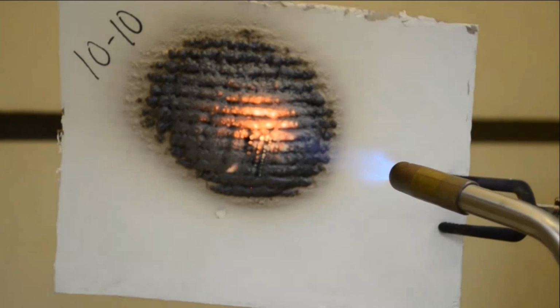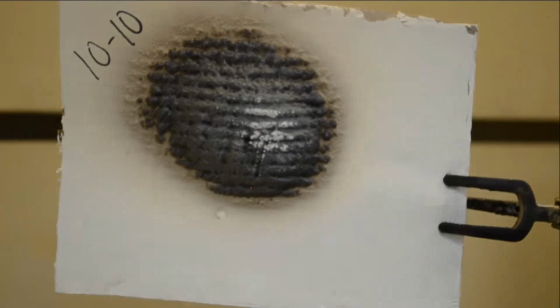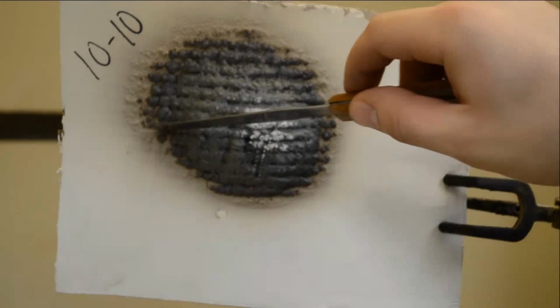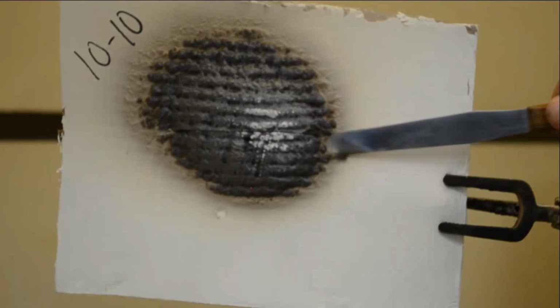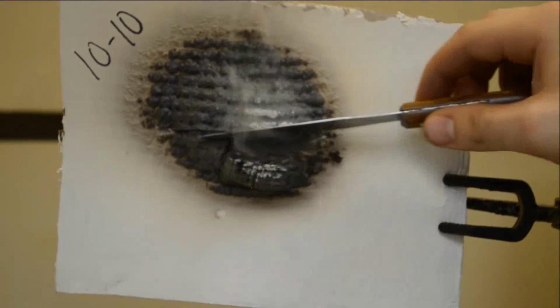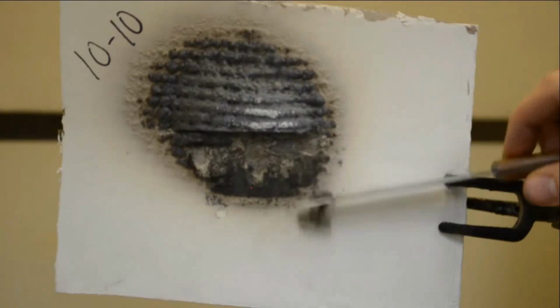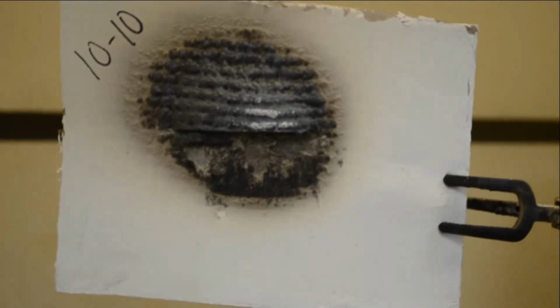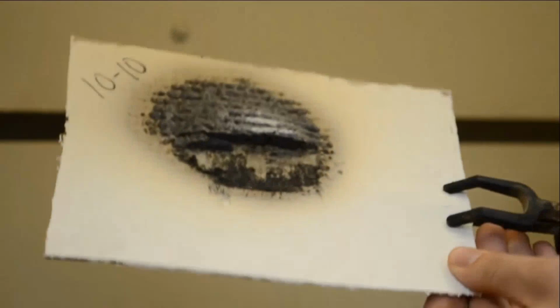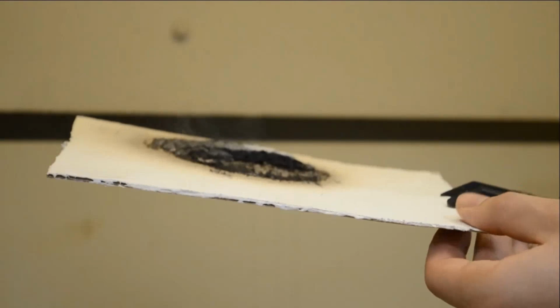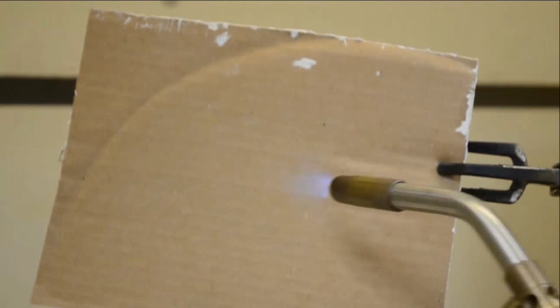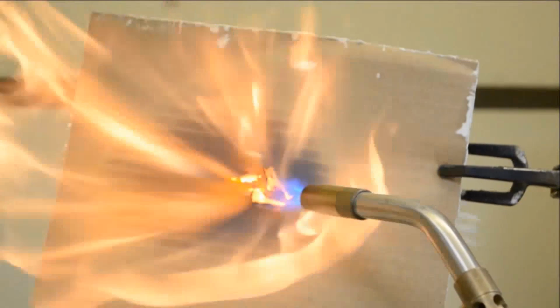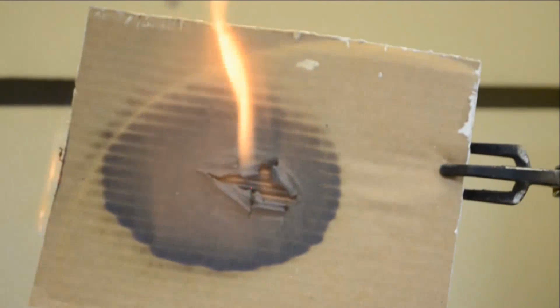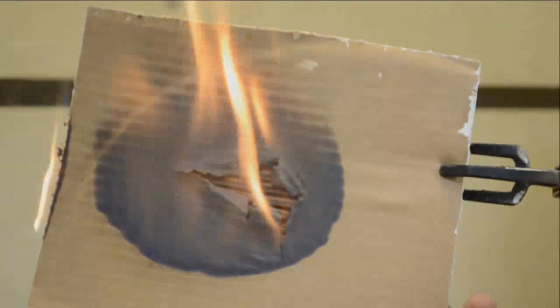As you can see, 1010 creates a layer of char that prevents the ignition of the cardboard substrate. As the char is removed, the cardboard substrate is revealed to be unaffected by exposure to direct flames. Turning the cardboard allows us to show the profile of the charred 1010 and exhibits the protective barrier that is formed. As we reverse the cardboard, the substrate is shown to be fully intact and unaffected by the flame. For contrast, when the uncoated cardboard is exposed to the open flame, ignition is almost immediate.